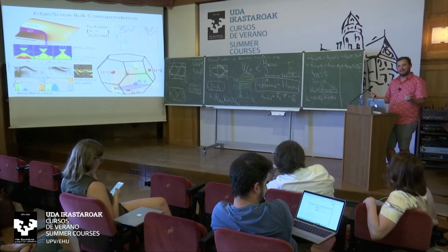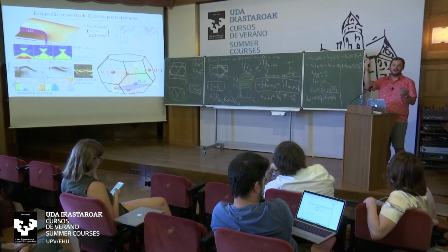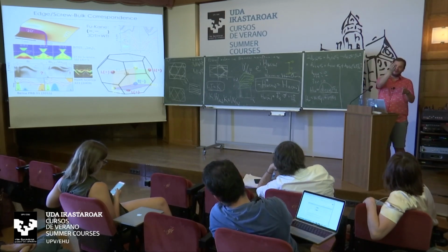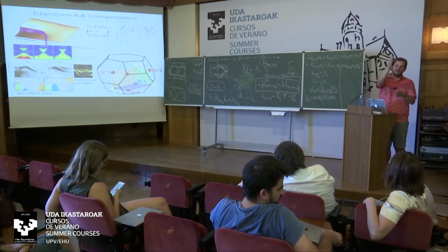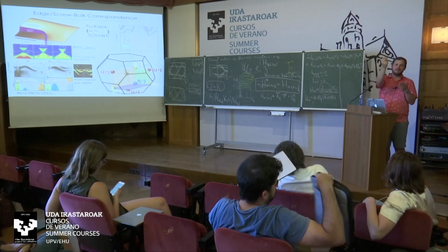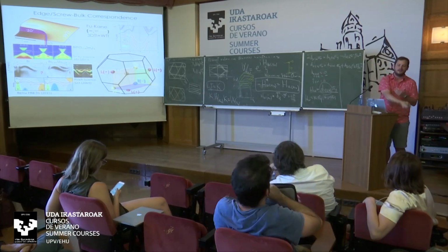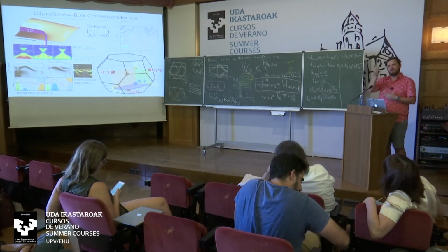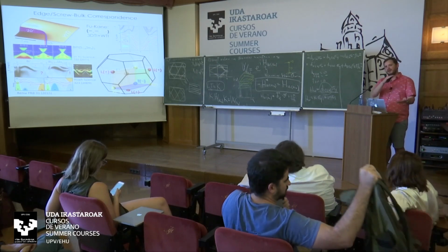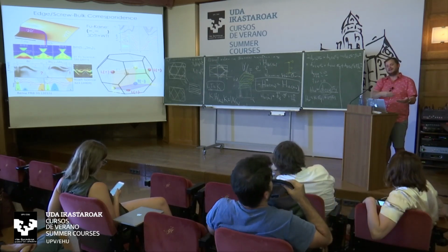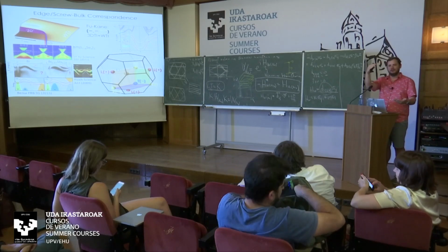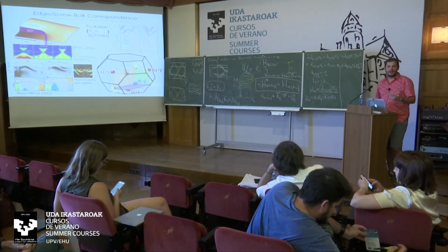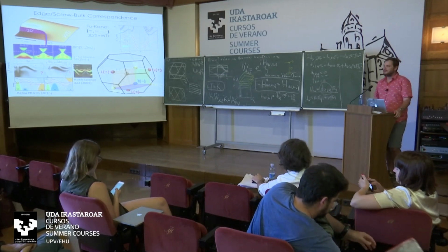Maybe this would be a more familiar picture to this audience. As you go closer on the Fermi arc, as you go closer to the Weyl node, the Weyl cones are gradually closing, and therefore the gap is reducing, and with it, the penetration depth of the Fermi arcs is diverging. It's exactly the same argument. How much the surface band penetrates into the bulk is inversely proportional to the bulk gap it sits on top of. So what ARPES measures is, of course, the surface band structure. It has some penetration into the bulk.